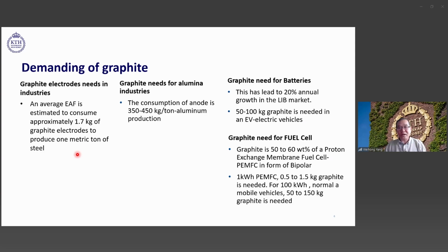In primary aluminum production, it comes from electrolysis to make the purification of the aluminum. That's quite a lot, about 350 to 450 kilograms per ton of aluminum. You can think about the big carbon emissions, for which so far there's no other way to reduce.